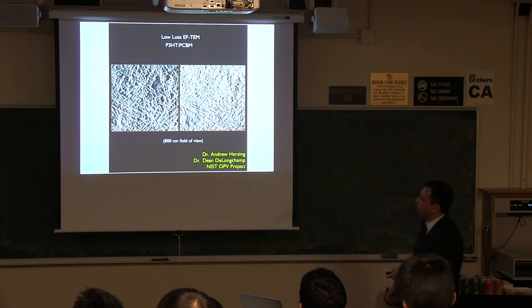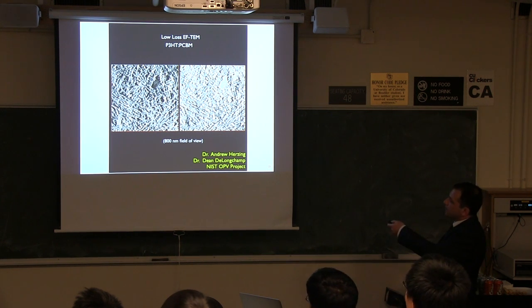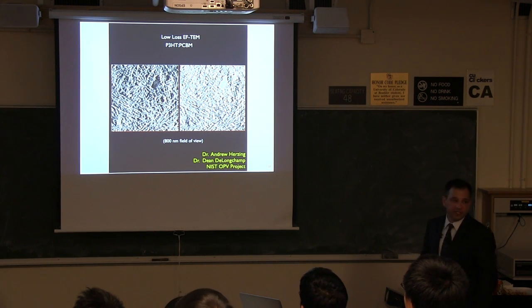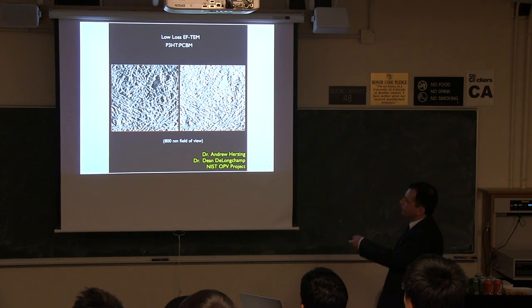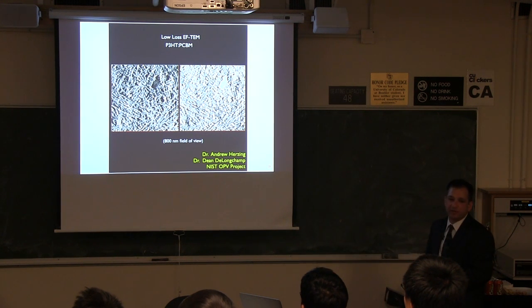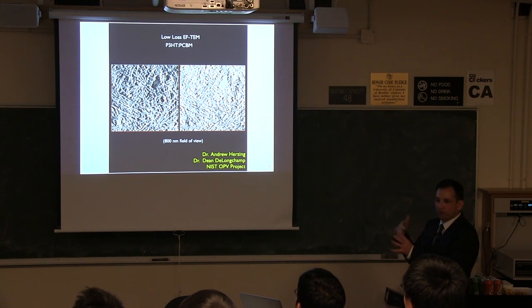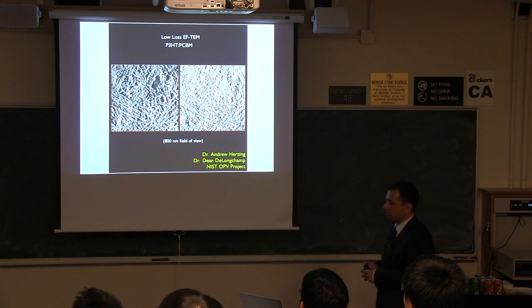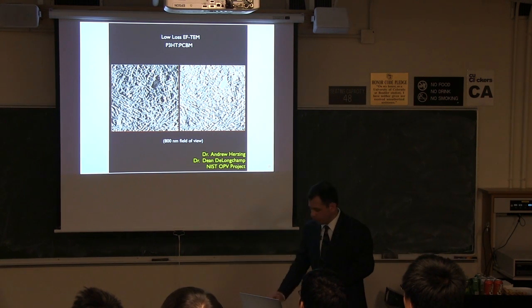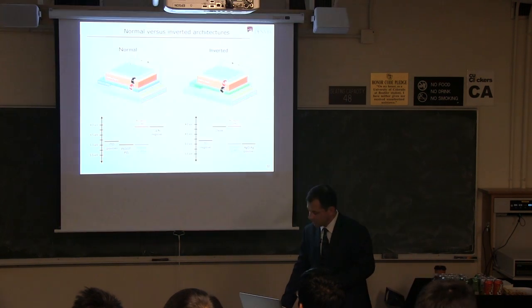So here you can see that you can separate out, again, the polymeric component from the fullerene component, and have a pretty good idea of what the thing looks like on a molecular level. Still not quite good enough. The resolution here is something like 3 to 5 nanometers, which really doesn't tell us exactly how polymer and fullerene are aligned at a nanoscale level. So that's something we're also working on. And we're working with the NIST group on using NEXAFS measurements for doing those. And Dean DeLongchamp has been helping a lot with those measurements.